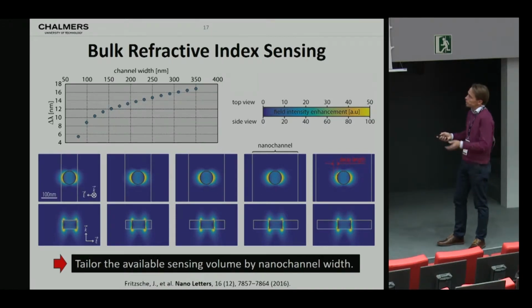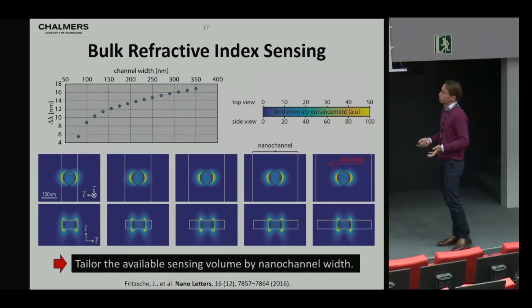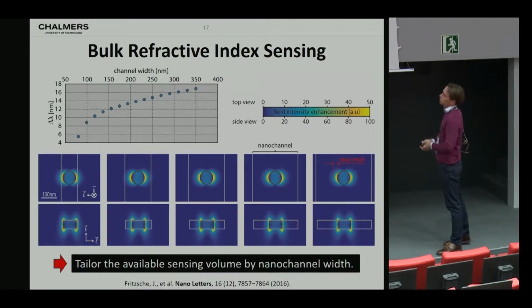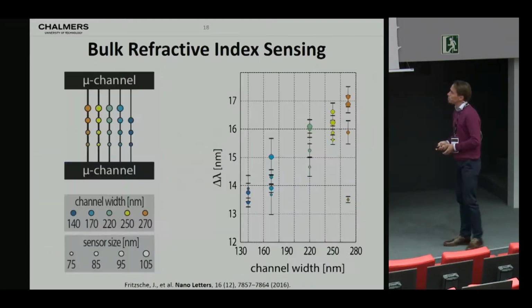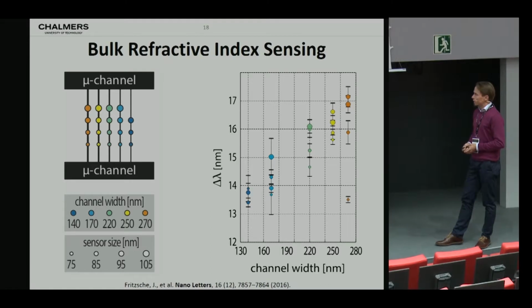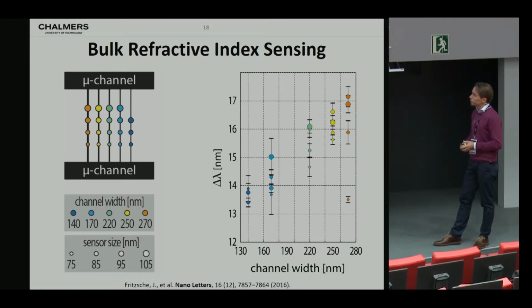So what you would expect is, if you make your channel smaller and smaller, you will decrease the bulk refractive index sensitivity because some of the sensing volume is already occupied by the walls. And this is exactly what you see in the simulations here for an 80 nanometer particle as we increase the width of the nanochannel.